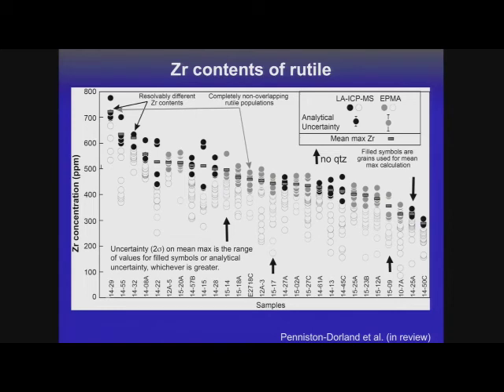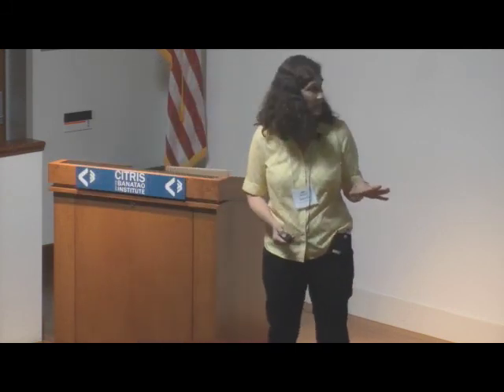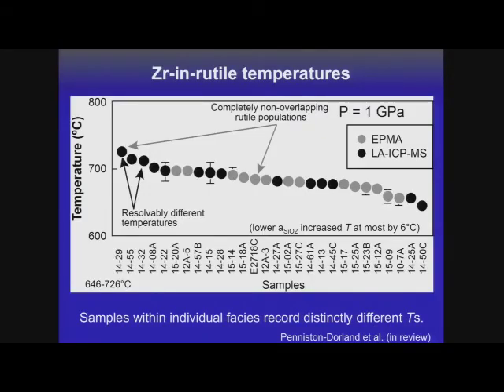So what you can see is that we get distinguishably, resolvably different zirconium contents. You can see the uncertainty of the two methods is shown in the upper right-hand corner. And of course you should be skeptical of this mean max zirconium method. You can see that we even get resolvably different populations. So this one here on the left has no overlapping zirconium rutile measurements with this one here on the right. So not only do we think we have resolvably different zirconium contents, but we have samples with completely non-overlapping rutile populations. So clearly different temperature conditions are recorded by some of the blocks in this melange. And here are the temperature conversions. What I showed you before was the zirconium content. So this translates again into resolvably different temperatures. And here are the different temperatures from the completely non-overlapping rutiles.